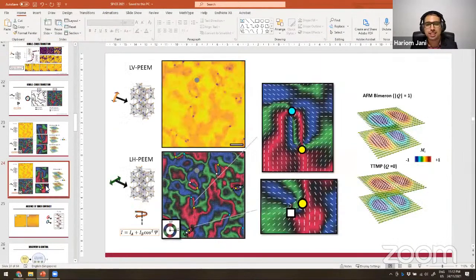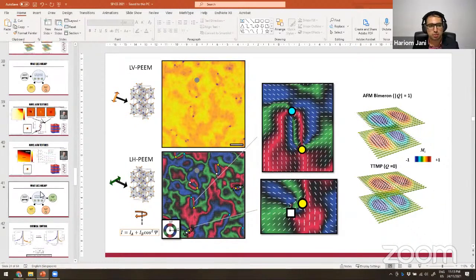We have actually tried to do pair correlation analysis of this, but unfortunately we found that the amount of defect density that we have does not provide sufficient statistics. But it is very straightforwardly possible to image, for example, in some of these cases, the intermeron distance. And we still feel that they are sufficiently sparse at the moment, but there is very clearly presence of some kind of binding between them. As you can see here, a meron-antimeron pair of this kind would actually involve some form of a domain wall, and the lowest length to which you can compress these objects and still have them stable is going to be determined by the energetics of the system. In some sense, this is also evident in some of the simulations that we've done.